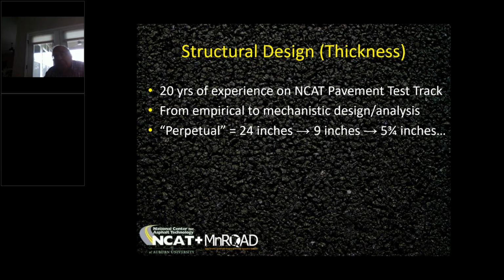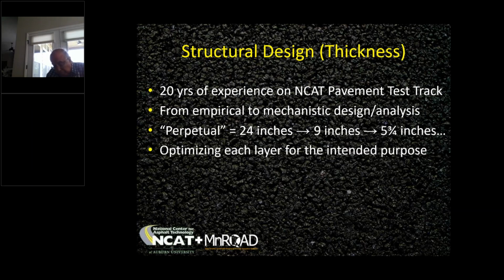And then we later found that using innovative materials like innovative additives, we could go as thin as 5 3/4 inches with highly polymer modified binder and still get perpetual performance, a pavement that will last forever if we just do shallow stuff on the surface. That's an incredible message, and that's with our base and with our subgrade. So you got to make an adjustment to those thickness criteria based on how soft the foundation is that you're working with.